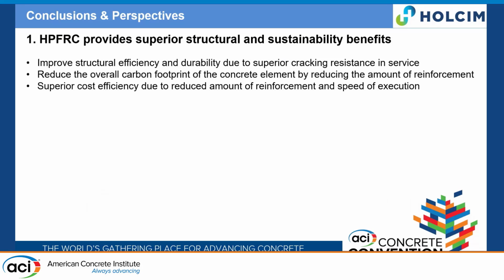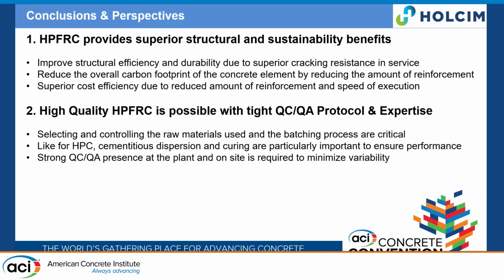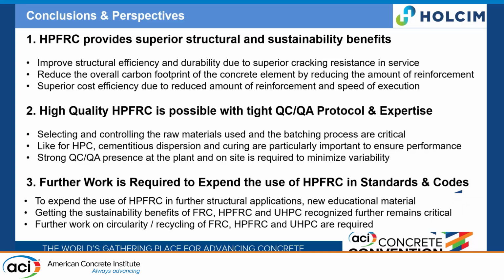So to conclude, this high-performance fiber reinforced concrete provides a lot of benefits on the structural and sustainability side, mainly by improving the durability and by being able to reduce the amount of reinforcement. It also provides a very cost-effective solution and speed. You can produce it in mass production if you have a tight QC/QA protocol and good expertise. This is mainly not only in the lab, but really in the production. You need to work very closely with the operation and with the customer to ensure you have proper curing also. This is fundamental.